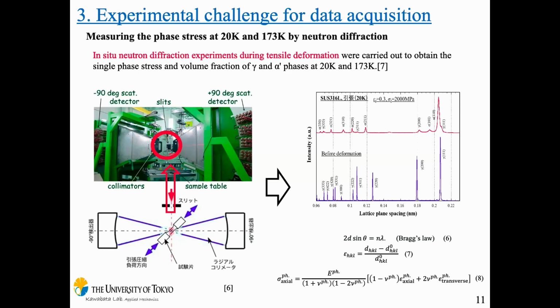So this is the experimental machine. And in this experiment, we irradiate this tensile specimen with neutrons of various wavelengths, and the neutron diffraction is measured. And the particular wavelength neutrons are detected strongly. And based on Bragg's law, equation 6, we can get the lattice displacement. And also from this, we can get the single phase stress using equation 8.